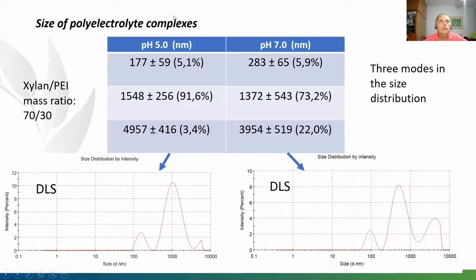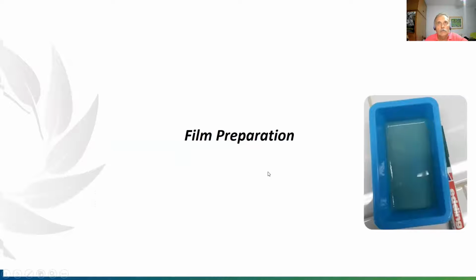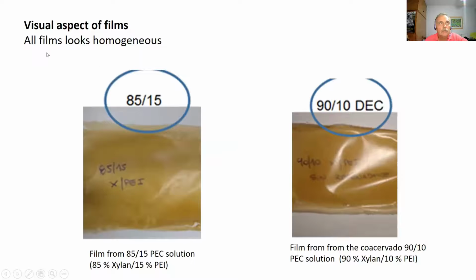How can we see the complexes? When we prepare a complex, the size can be determined. In this case, for 70-30 mass ratio, we can see that the main fraction has around 1,500 nanometers, because we have a mode in the size distribution, according to DLS measurement. So we can prepare the films and see how the films are, and we can see that all the films look homogeneous. Here we have a film obtained from the whole solution, and this is a film obtained from the coacervate.